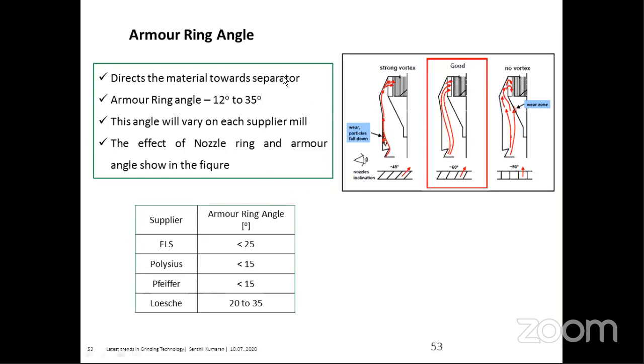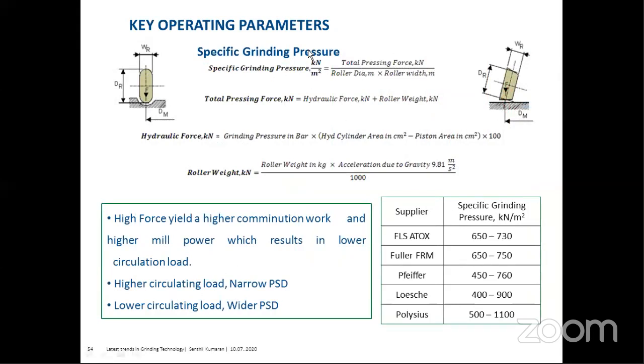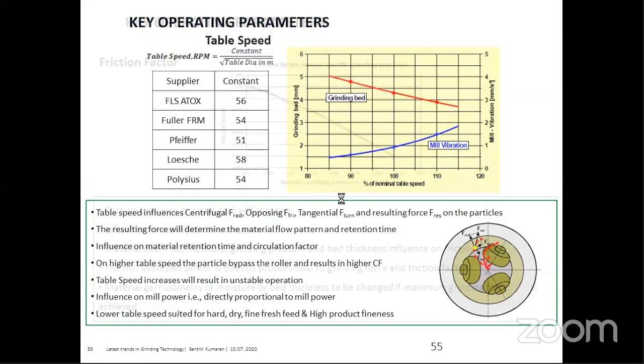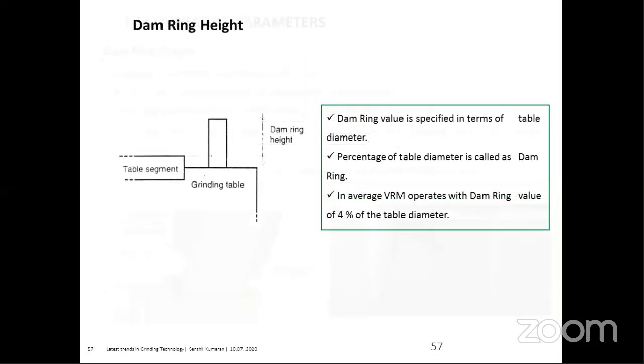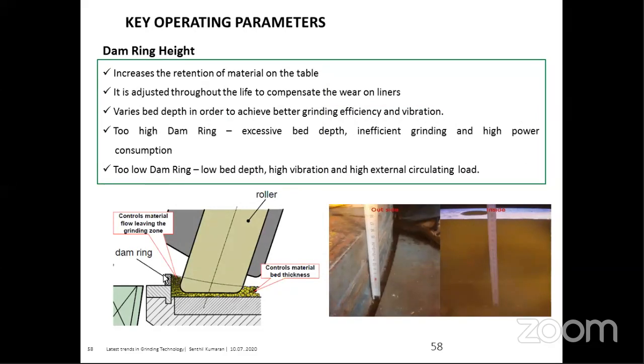There are many suppliers for the raw mill: one is FLS, one is Polysius, Pfeiffer, and Loesche. They are different suppliers, and everyone has their own specifications for the mill. The grinding pressure defines the total pressing force, the roller diameter and the roller width, and different suppliers have their own norms. This is the dam ring. The dam ring height is taken as a trial or optimizing parameter. We decide the size of the dam ring based on the grinding system. If the dam ring height is kept too high, then the bed depth increases, which leads to inefficient grinding and increases the power consumption as well.